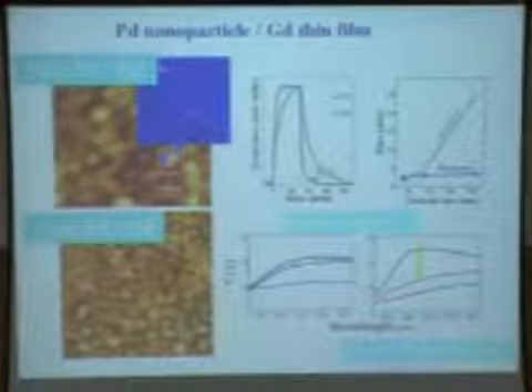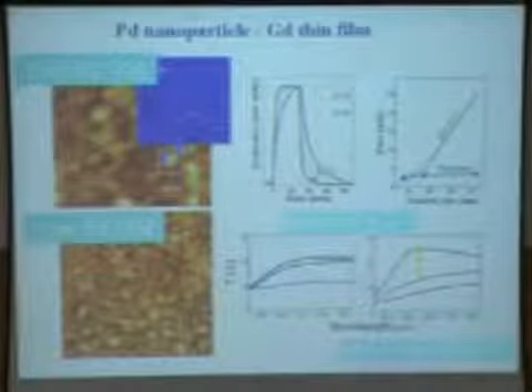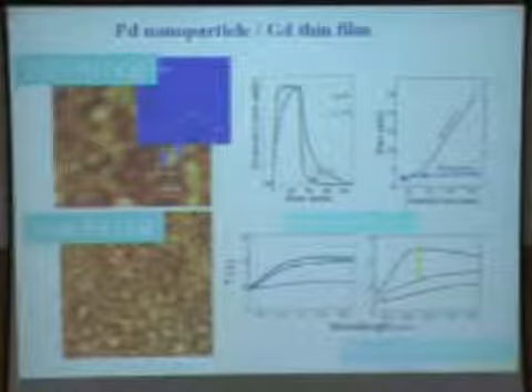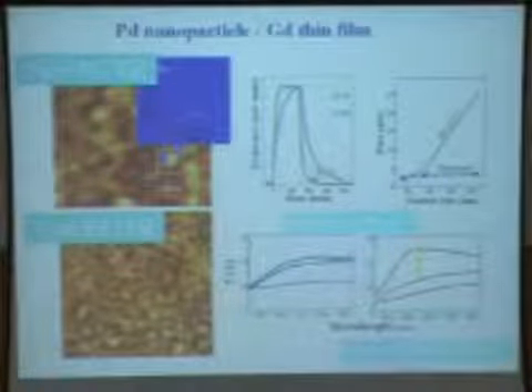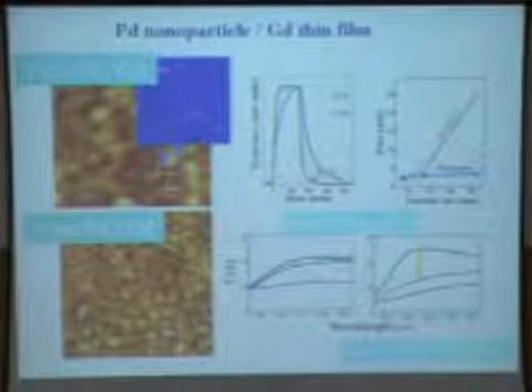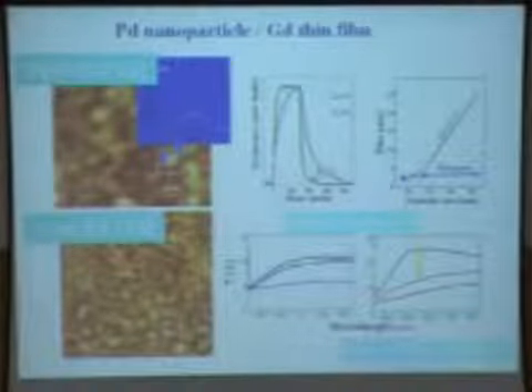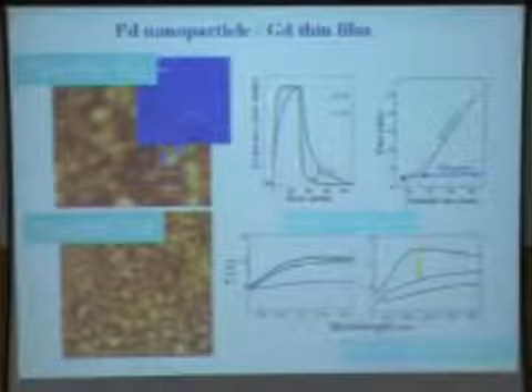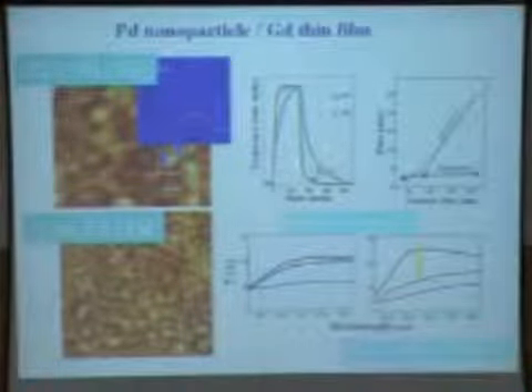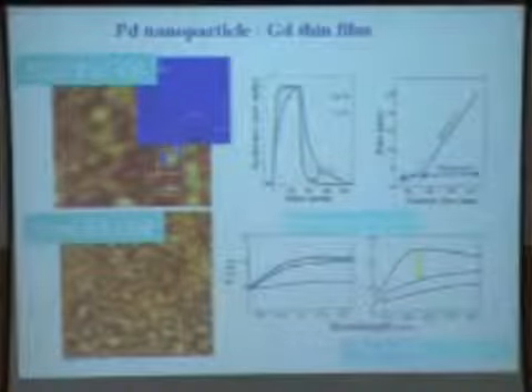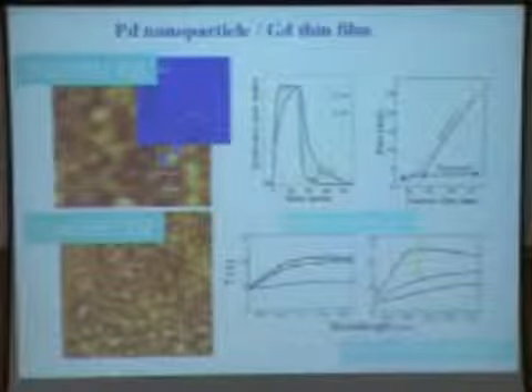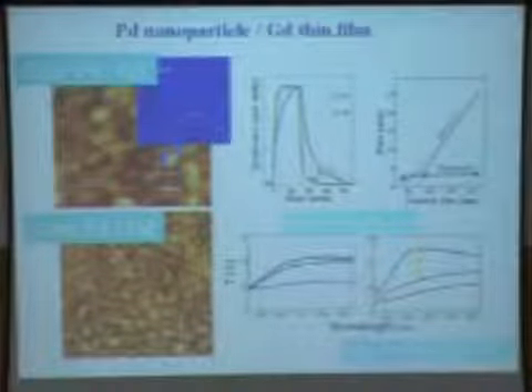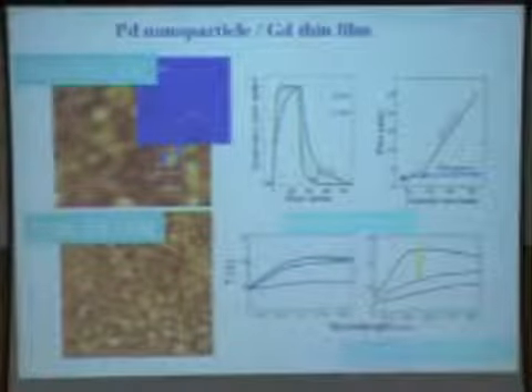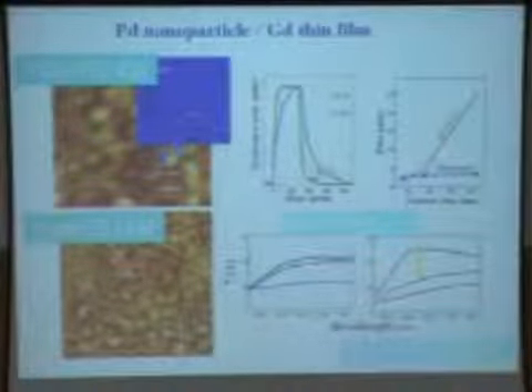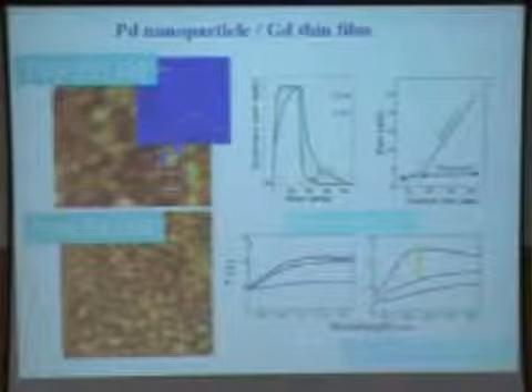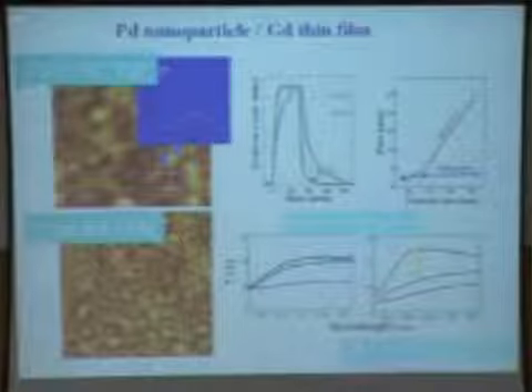This is the second system which I was mentioning, where we just put palladium. In the second system we only have an underlying thin film, and we removed the palladium thin film and made a palladium nanocrystalline layer. And you can see, this is what I was mentioning, this is the switching time. In the red curve, if you follow the red curve, the switching time is very fast, and the material comes back to its normal state also very fast. If you look at the blue curve, it's going very slowly, and also it is coming out very slowly. So this part is switching, this part is recovery, and it is shown here how the response and recovery time changes as a function of average crystallite size. This is very important.